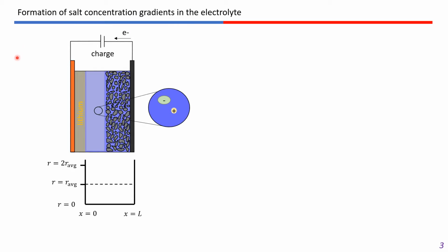The reason this question is important is because at high current densities, significant salt concentration gradients will develop across the electrolyte. Here I'm plotting the local salt concentration as a function of position in the cell, and if we apply a potential across the electrolyte, anions will be attracted to the right and cations to the left in the direction of the electric field, but because anions cannot react at the electrode and electroneutrality must be maintained, this results in the formation of a salt concentration gradient across the electrolyte.